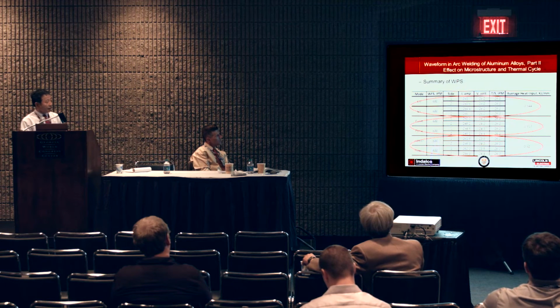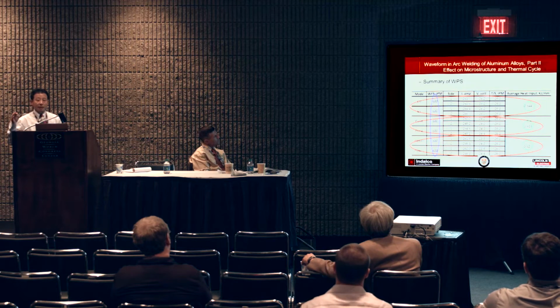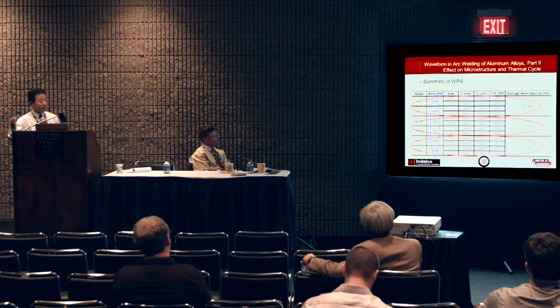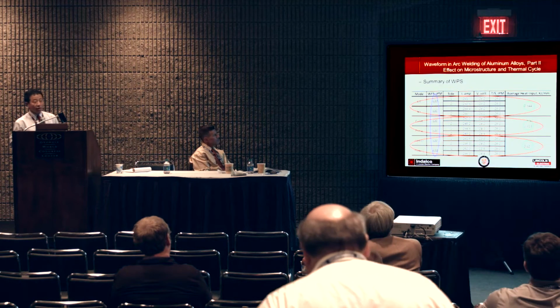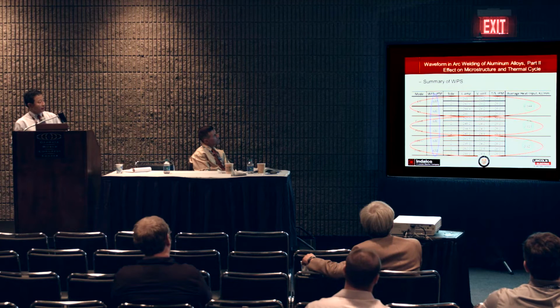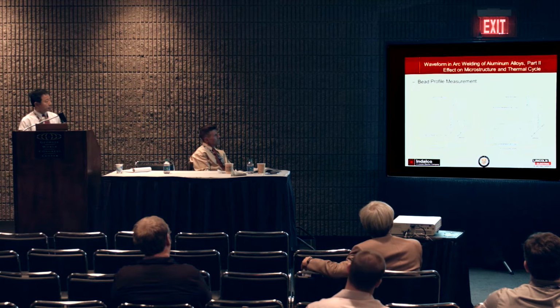And it's very interesting, I tried to compare things. Basically, I chose the same wire feed speed, which gave us exactly the same productivity, same travel speed. However, different modes gave me different current and voltage. But if you look at the last column, my heat input is fairly close. I cannot do exactly the same, but very, very close.